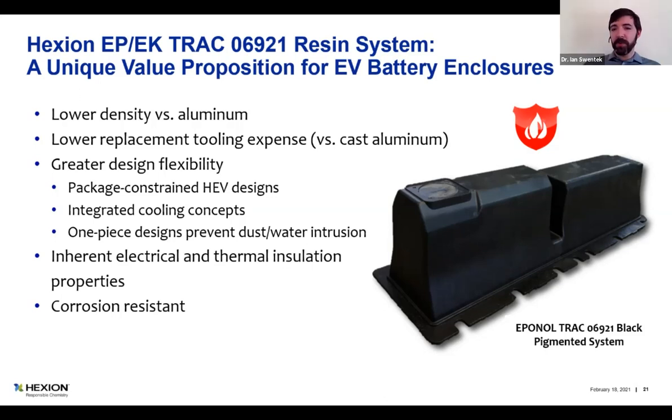So what's the typical total cycle time? I produced the part on screen in about a 3 minute cycle time. So a two and a half minute cure time with about 30 to 45 seconds of charge loading and part unloading. And that was in sort of a laboratory sense. In a fully automated scenario, you would realize a similar, if not better, cycle time for a part of this size. So this is a roughly 1.2 meter long by about 0.4 meter wide part, just to give you sort of a footprint, weighs about 7 kilograms. In Imperial, that would be 4 feet by a foot and a bit by another foot and a bit, and weighs about 15 to 16 pounds. So it's not a very large part.